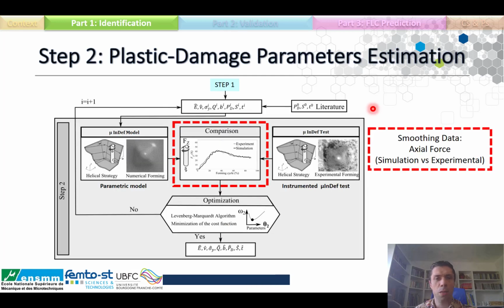From the identification by a tensile test, we now have the elastic and plastic parameters. However, we still need the damage and fracture parameters in order to start our identification. These damage and fracture parameters are obtained from the literature. With this set of parameters, we can perform our micro-in-depth simulation, and thus we obtain the numerical forming forces. As explained before, by performing a micro-in-depth experimental test, we obtain the experimental forces. In the same manner as we did for the tensile test identification, we use our optimization toolbox to achieve the parameter values which have the least difference between the simulation and the experimental ones.